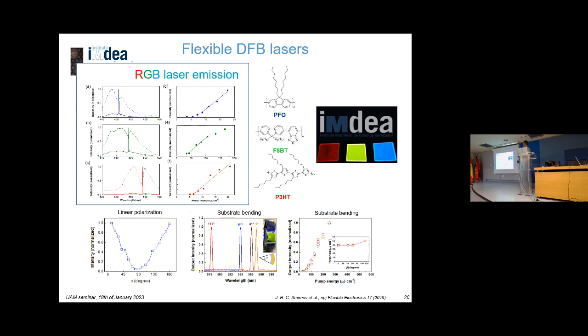These are, for instance, three different polymers with emission in the blue, green, and red, with polarization properties. They are linearly polarized, and something you can do because they are plastic is bend them, and you can see a slight shift of the single modes of emission upon bending.